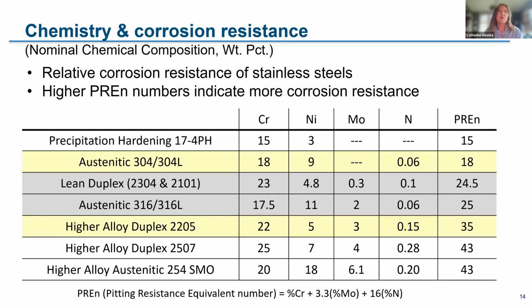You can calculate what we call a pitting resistance equivalent number, PREN, based on the chemistry of the stainless steel. This gives you a relative ranking of the stainless steels. It is useful for understanding the relative corrosion resistance, but it's also very important to understand that those numbers may not tell you which alloy would be better for a specific environment. So you have to go a step further, but if you're trying to explain the difference in overall corrosion resistance between, let's say, 316 and 2205, it's a pretty handy tool.